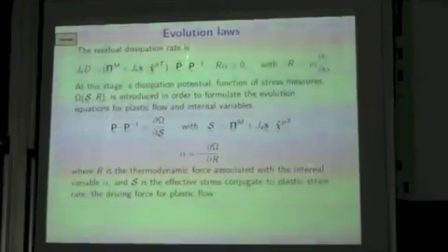We have also a hyperelastic relationship between the relative strain here and the relative stress. Okay, the residual dissipation is due to plastic slip here. We have the plastic slip rate, we have the usual driving force here, and you have a new term. The coupling comes into play here based on this relative stress.